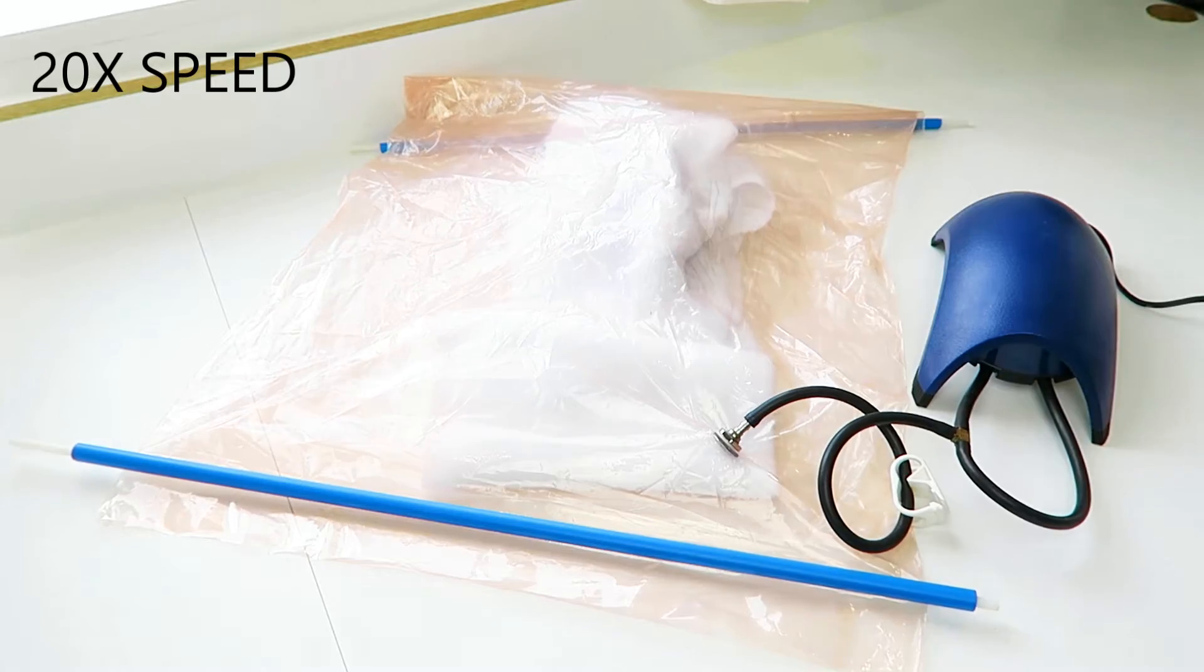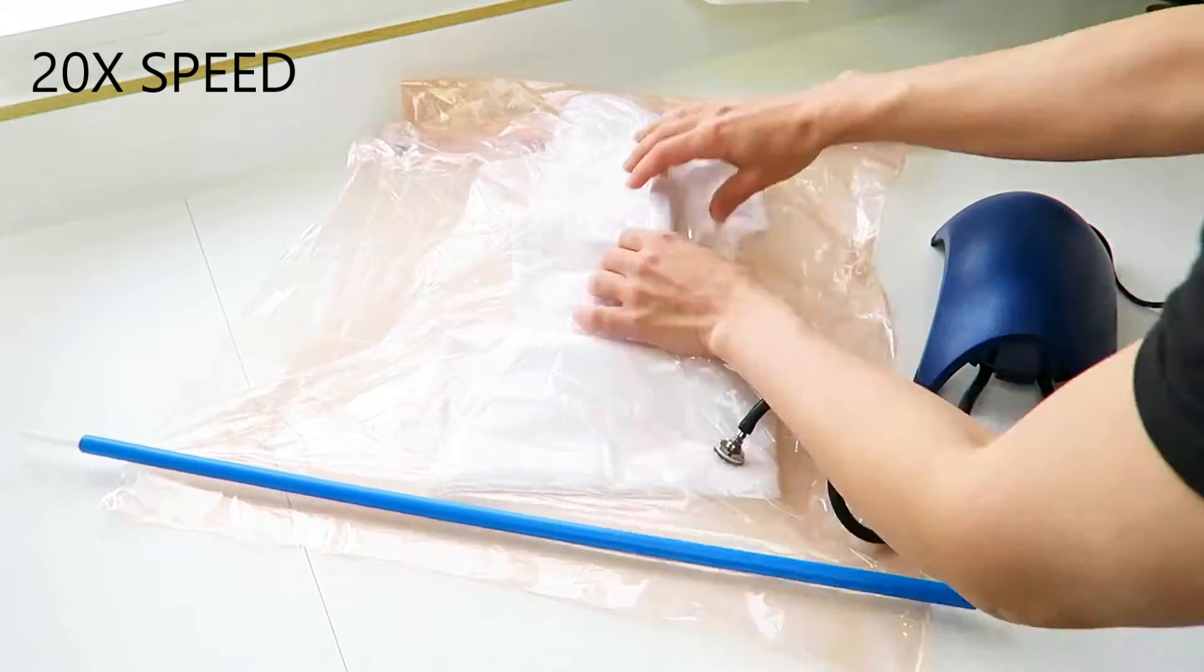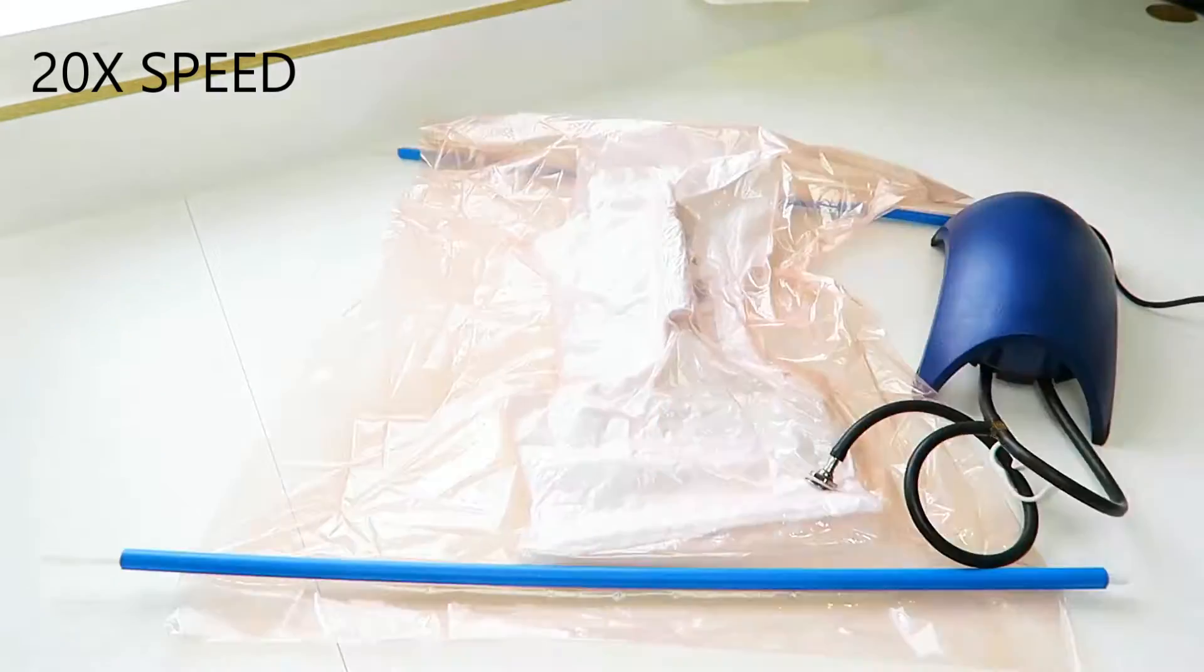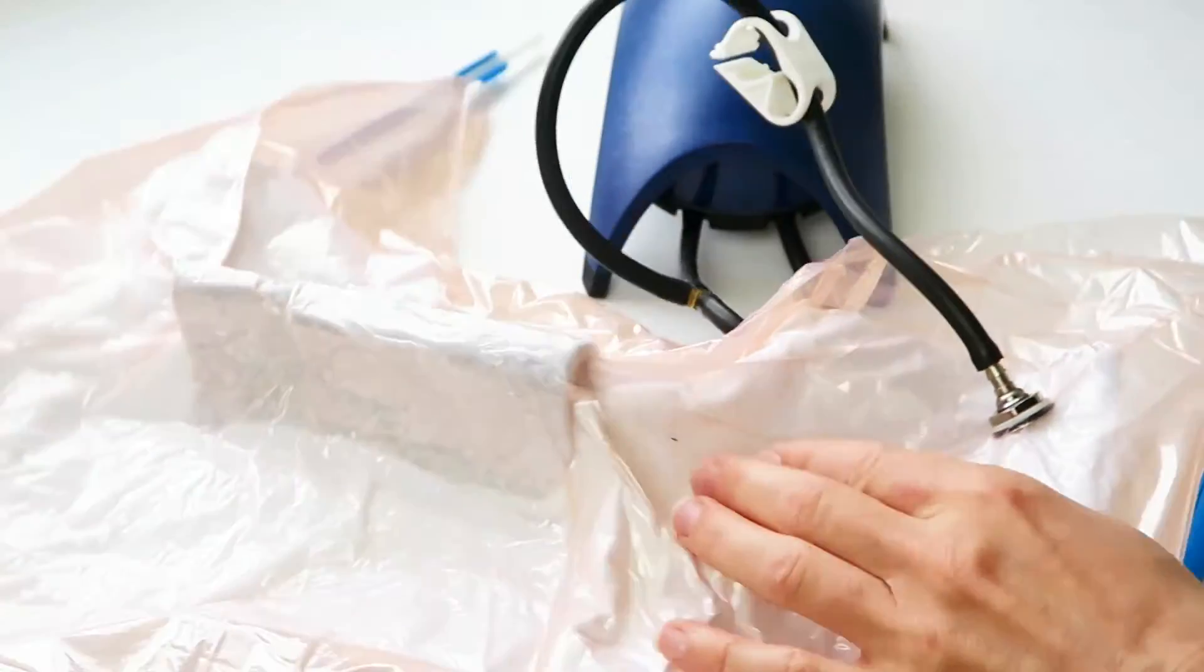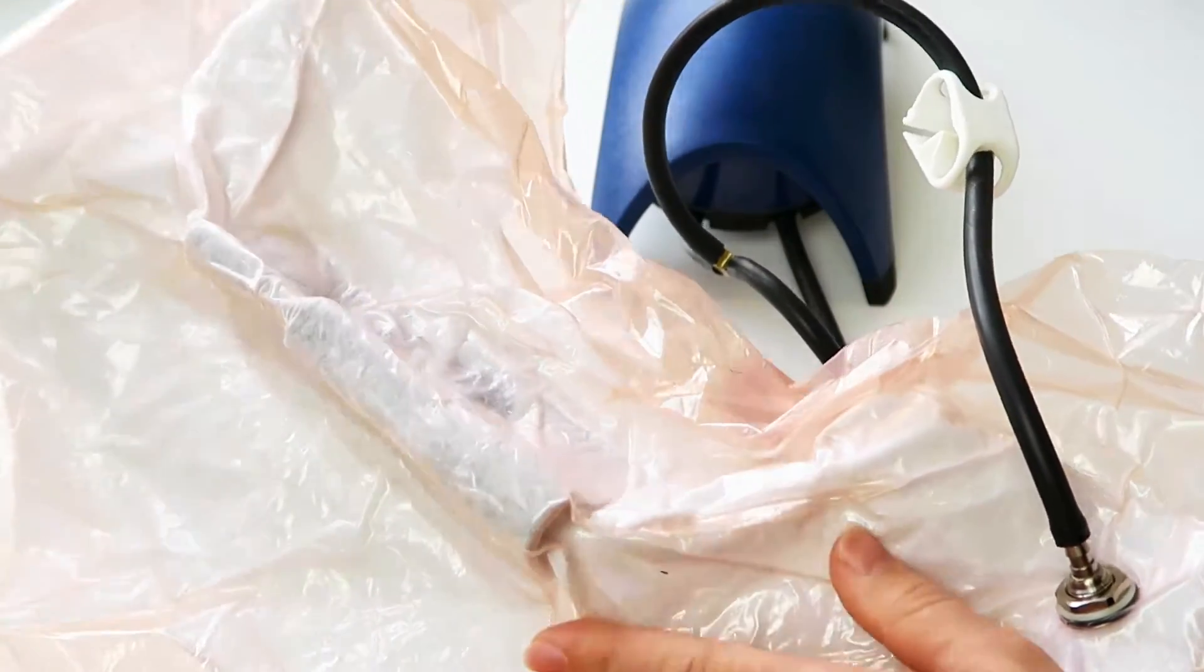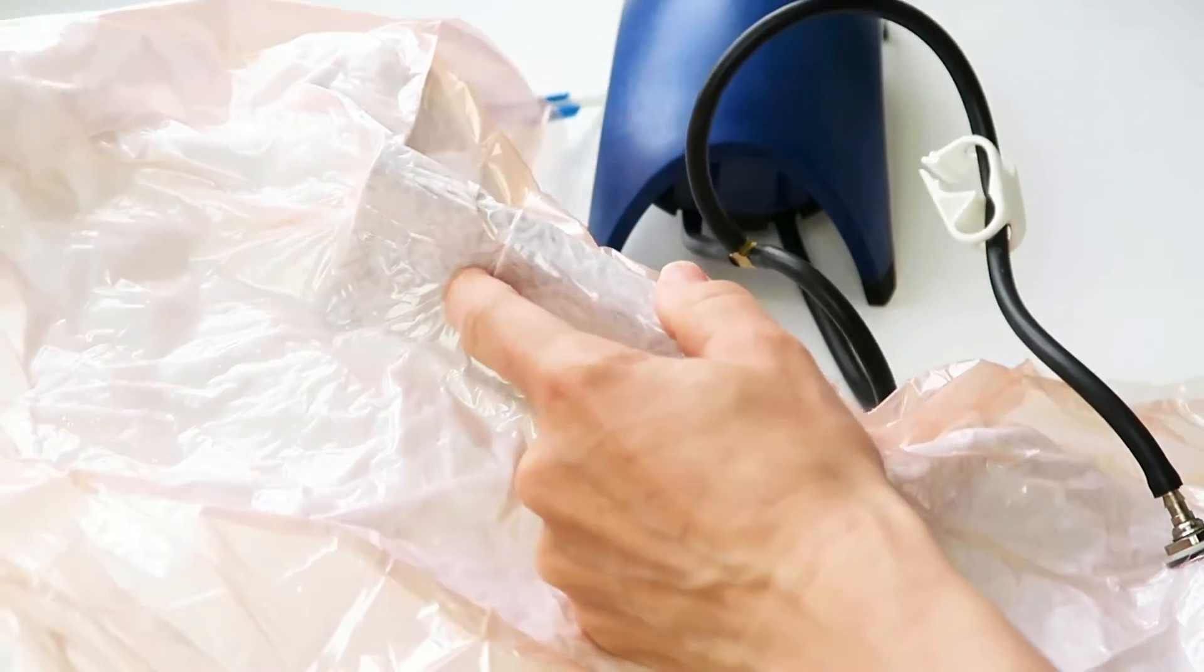It can take a while for the pump to suck out all the air, but once the bag is pulled down, this will help to remove trapped air and excess resin, and compress the carbon fiber into the mold. You can leave the pump to run continuously while the part cures.